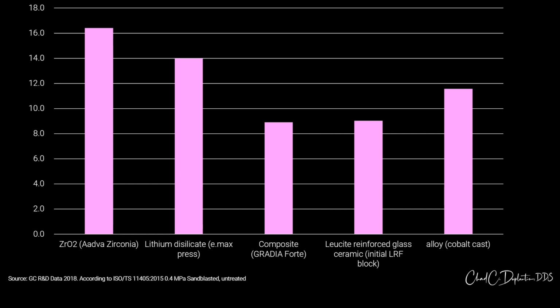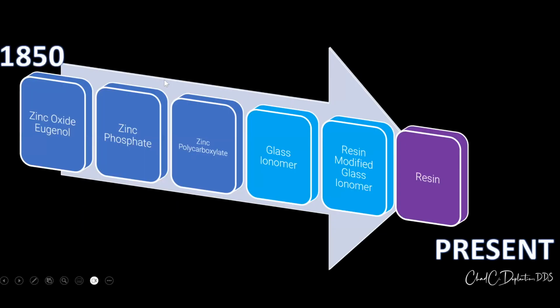And you're going to get similar bond strengths on the tooth. You're going to see 8 to 12 megapascals, I would say, of bond strength to the tooth. So you're going to get a good bond strength to the restoration, and you're going to get a good bond strength to the tooth, which really helps us when talking about luting strength. And so once again, for a retentive preparation and for the appropriate material, I would strongly recommend a resin modified glass ionomer.